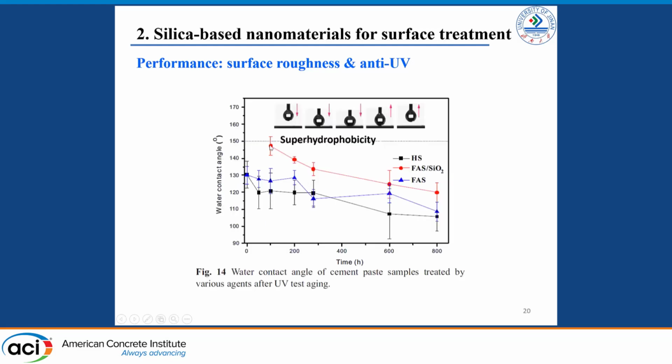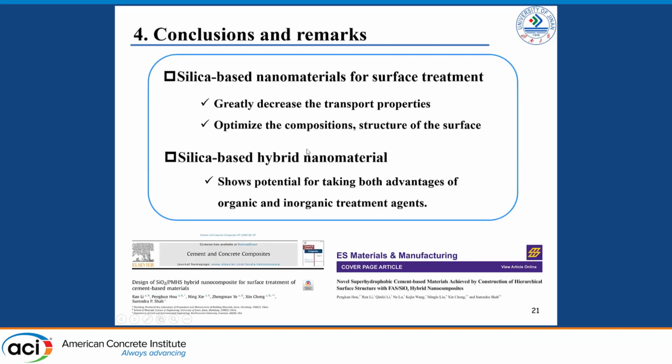So with this, we can see that superhydrophobicity, with a contact angle of about 150, can be achieved by this hybrid material, and it will behave better in the UV testing aging simulation work. So with this, I will conclude.